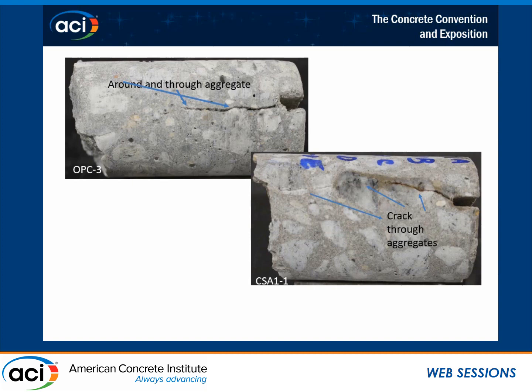Bottom bar is down here, and we're getting effects of this crack on the bottom bar. Stopping here, we're also seeing a reduction in chloride as we go down. So it's not uniform. You can see the cracking here is through the aggregate and around the aggregate. It's pretty strong concrete. Now, in the case of one of these calcium sulfoaluminate cements, you can see the crack coming down. It went right through the aggregates because this concrete had much higher strength than that concrete at the time that we did it, and this went through the aggregates as one would expect.